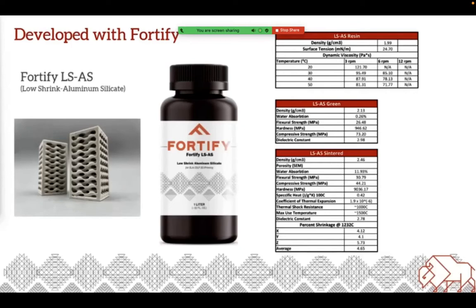Going back to shrinkage and how not fun it is, we've seen this material used a lot for setters and fixtures. There are many issues with MIM parts warping, and even significantly more issues when you look at metal binder jetted parts warping. This material is great to be used as a setter, sacrificial part, or waster plate for other metal objects. If you're getting started in ceramic additive, this is the material to start with, as it has material properties that cover a large swath of applications and parts.